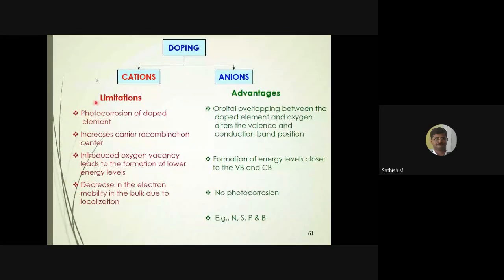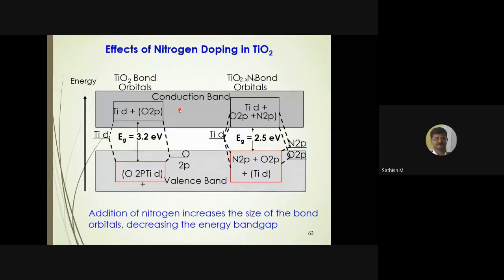Another important thing which comes up recently is anion doping. Cation doping is well known. Recently, anion doped TiO2s, with sulfur or nitrogen, are slowly coming up because of the change in the band gap. This anion doping is completely different from cation doping. Over the last few years, maybe more than 10 years, you could see this area is almost saturated with nitrogen doping or sulfur doping or boron nitrogen co-doping systems. The co-doping system essentially alters the band gap. That is the only thing we have to see here.